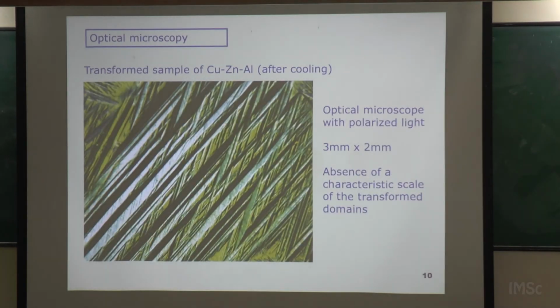If you go to this picture, this is a copper zinc aluminum. This is a sort of brass alloy that has been transformed below the martensitic transition temperature without applied stress. And what you see here is the surface, because these new domains reach the surface, and then they do some small deformations there that you can see using polarized light, okay? The different colors, every color is what's called a martensitic variant, an equivalent variant, just changing some symmetries, okay?